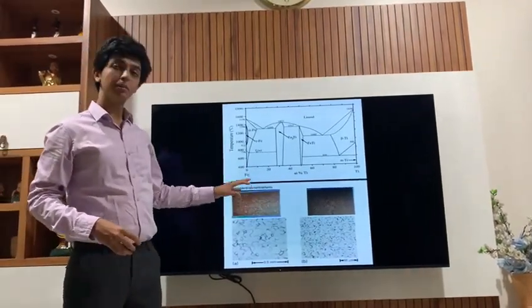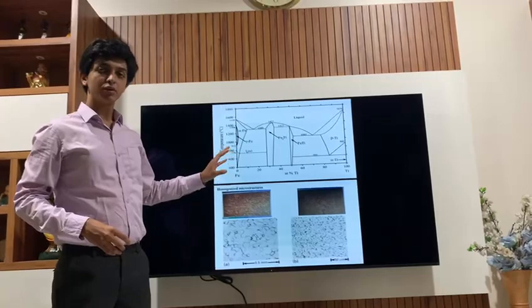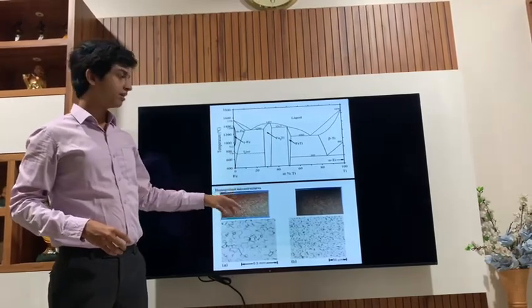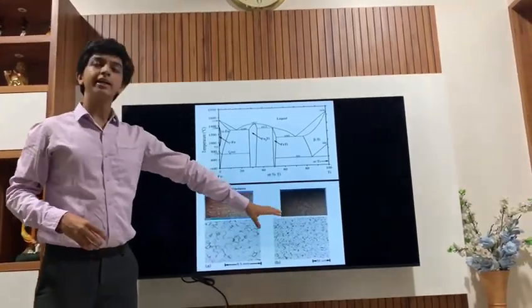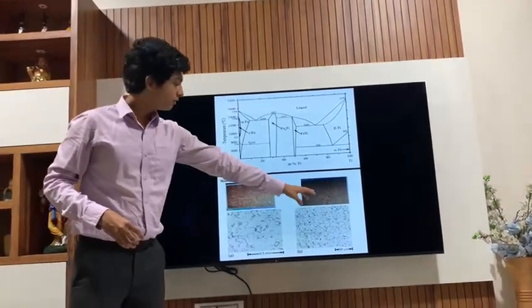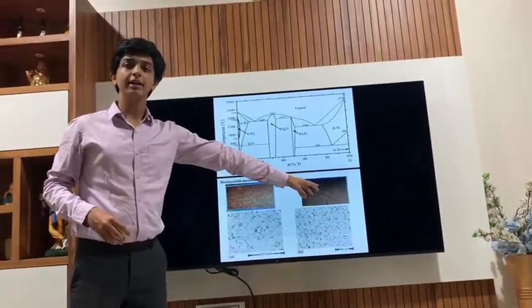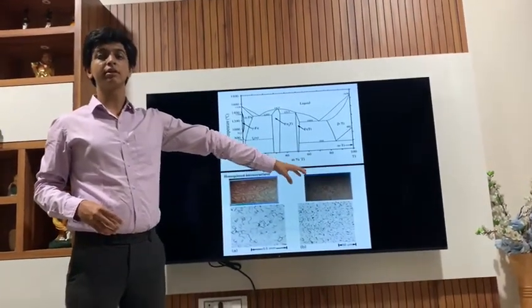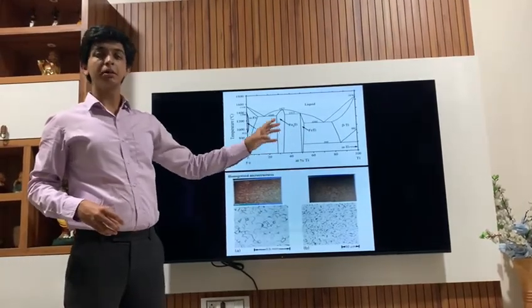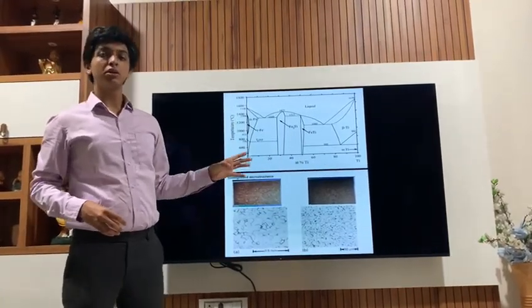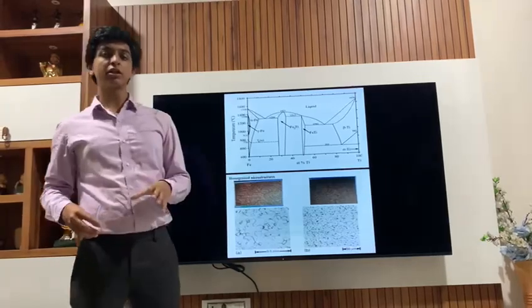There was no issue with the pure titanium structure as it was a complete single alpha phase, but there was an issue with the iron titanium alloy. As we can see, there are needles in the microstructure which suggest that the specimen might be brittle. But we were allowed to continue with the next step, which was the metallographic polishing.